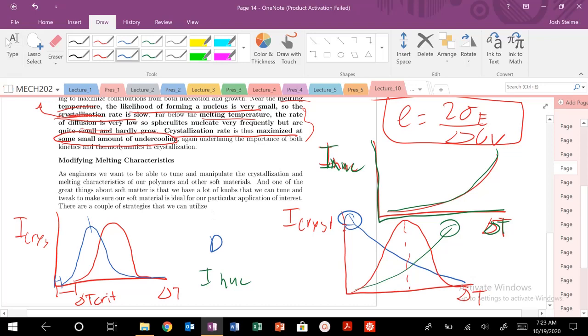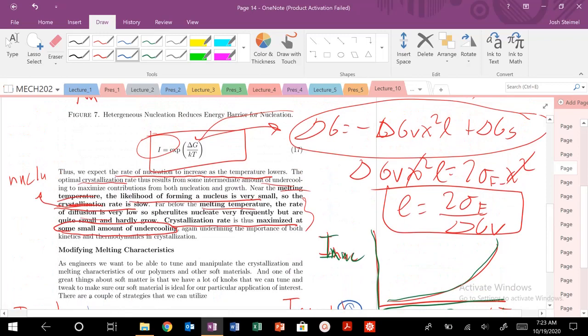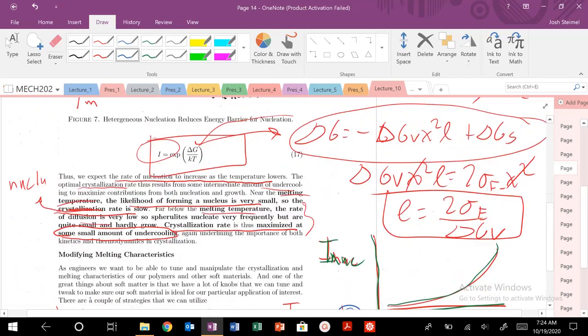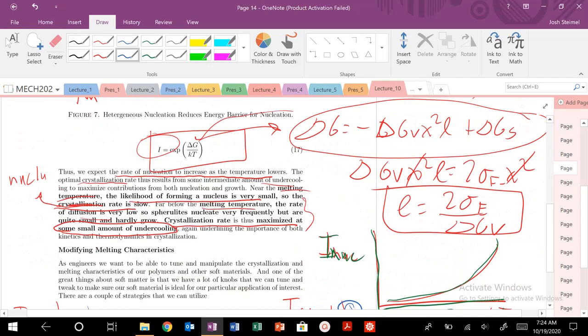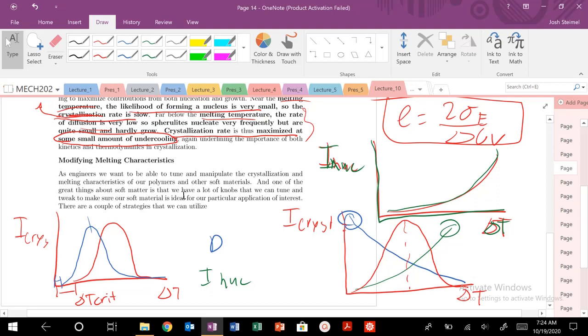So a lower amount of undercooling, again, because if you look back at my ENGR 45 notes and some of the videos that we posted on nucleation and growth, heterogeneous nucleation, basically there are these little defects or parts of your system where you could start to nucleate. Usually it's at the edges. There are some surfaces where it's favorable to start to nucleate your particles. So your energy barrier is lower for heterogeneous versus homogeneous, and thus you need less delta T, thermodynamic driving force,